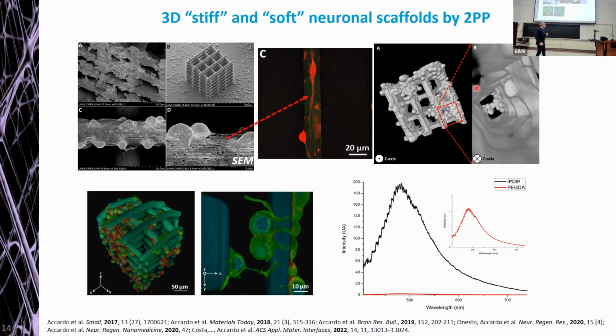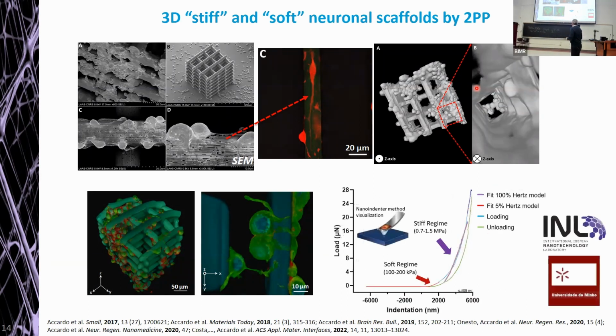But when I arrived at TU Delft, we are a faculty of mechanical engineering. So we are also interested in probing the mechanical properties of this material. And this is what we did in collaboration with the International Iberian Nanotechnology Laboratory in Portugal, where by using nano-indenting techniques, we characterized the mechanical properties of 2-photon polymerized PEGDA. The most interesting thing that we found out was that the 2-photon polymerized PEGDA has a dual stiffness regime, or let's say areas. The inner core, which features a Young's modulus in the range of 1 megapascal.